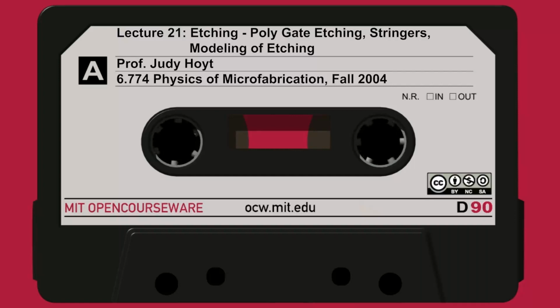So this wafer had no topography, so they etched the gates on perfectly flat wafers, and the yield was very high.